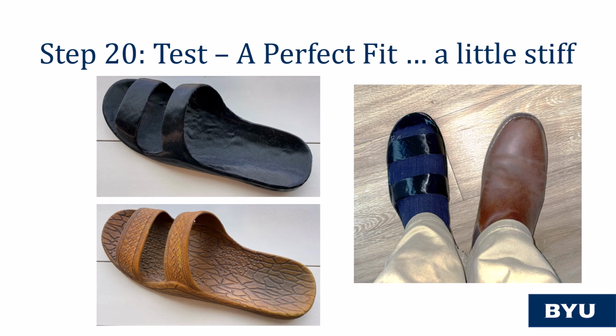Comparing the final part to the original shoe, the model maintains all critical geometry and matches the user's foot perfectly. The shoe demonstrates a lower stiffness relative to the bulk material, but the rigidity is still greater than desired. This is likely due to the shell that was added around the lattice structure to make it manufacturable, and subsequently added stiffness that was not anticipated by the model. Overall, the preliminary design can be considered a success.